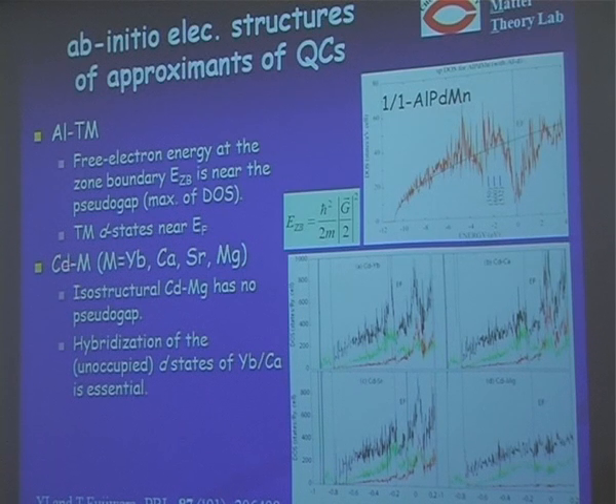And this is another example, the cadmium, ytterbium, calcium, strontium, and magnesium system. And this is the calculated density of state for the approximants: cadmium-ytterbium, cadmium-calcium, cadmium-strontium, and cadmium-magnesium. And you see we have a very shallow pseudo gap near the Fermi level for ytterbium, calcium, and strontium, but we have no pseudo gap at all for the magnesium.